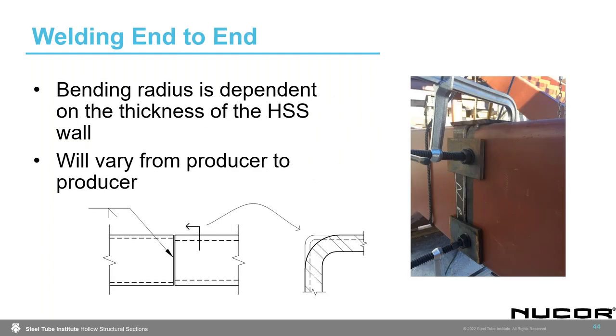When we're welding to HSS end to end, so if this is a column section and we're trying to transition from a thicker wall to a thinner wall, we need to again be cognizant of the fact that the bending radius of those corners is dependent on the thickness of the tube. It's also going to vary from producer to producer. So when you're calculating the amount of weld that you have or the amount of bearing that you have in something like that, you need to be cognizant of that.